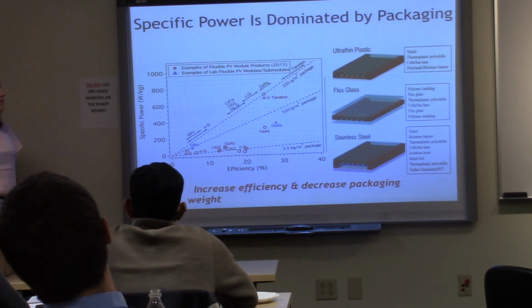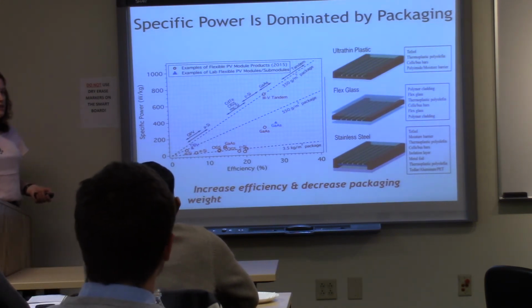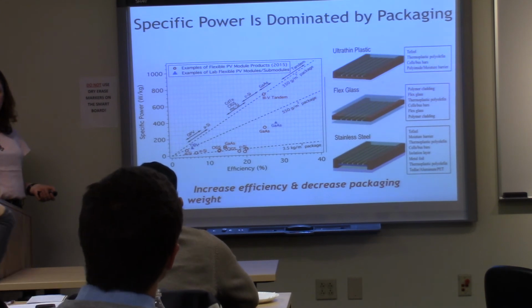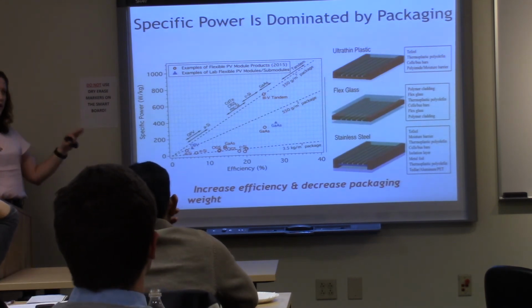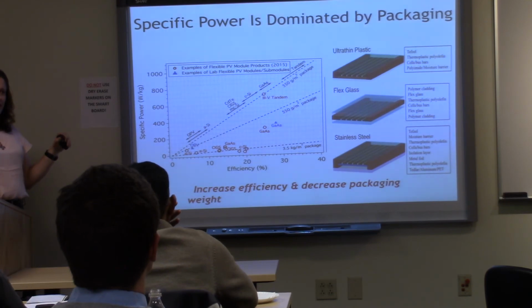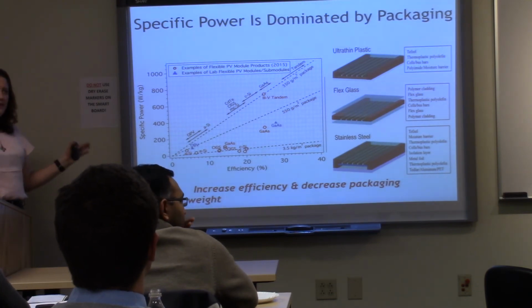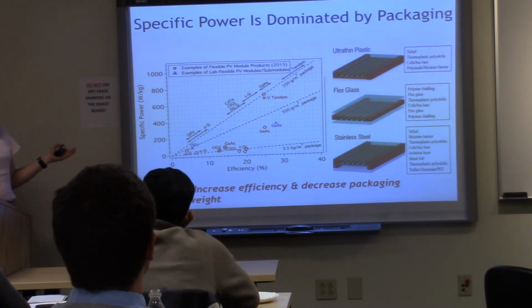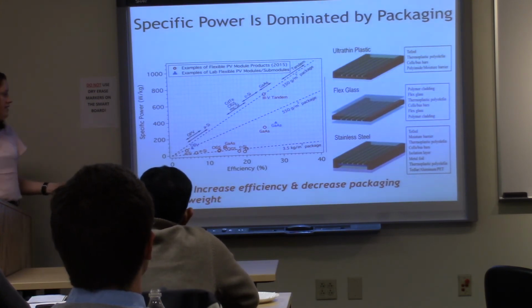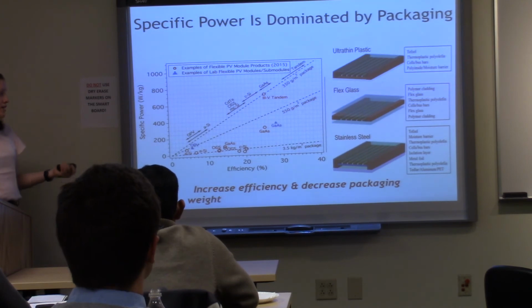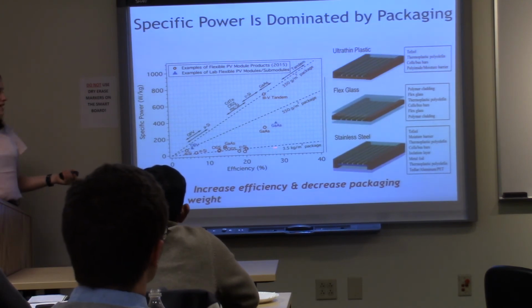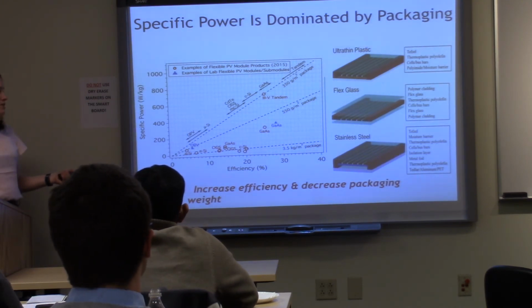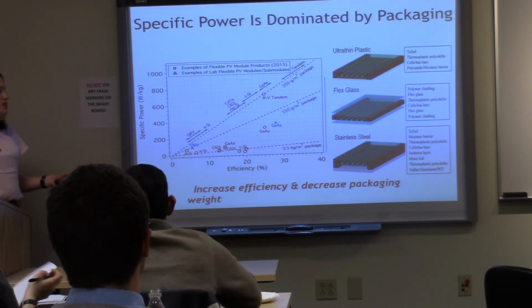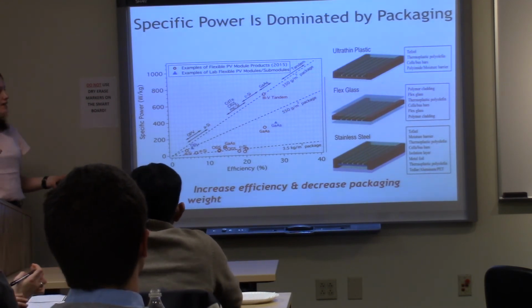What's important to think about in specific power is we've had people tell us that the TCO, the oxide coating weight, is what they think controls the specific power in a cell. And that's nuts, because what really controls the cell weight is the other stuff, everything but the cell. In silicon, you're going to have something a little heavier because you have a wafer. So here's a line for about 3 kilograms per meter squared with a full package. But it's really your substrate, your packaging, all that other stuff around it.